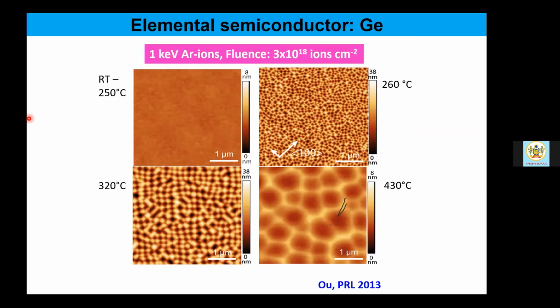The moment we increase the temperature by 10 more degrees, we start seeing the checkerboard pattern formation. And as we increase the temperature up to 320 degrees centigrade, the checkerboard pattern gets dimensionally enhanced. And at 430 degrees centigrade, this inverse pyramid formation takes place.